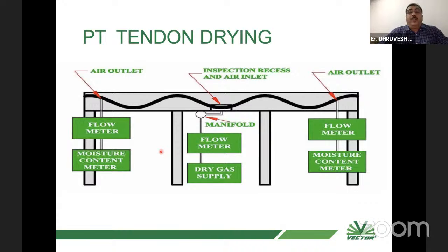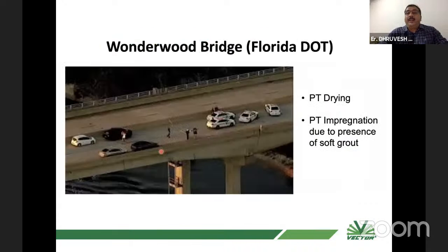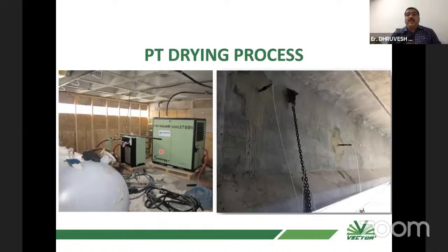It looks very simple, but it's a bit complicated. Complicated in the sense that somebody has to make this arrangement. You cannot use a simple cylinder of nitrogen gas or a balloon gas for that; you can use that for evaluation. But when it comes to the drying process, you need a huge amount of dry gas to be pumped. So you need a plant which can produce dry gas. You can have an air compressor to produce the gas, then a dryer, and you need to see that the dew point of the gas is around minus 20 or minus 30 degrees.